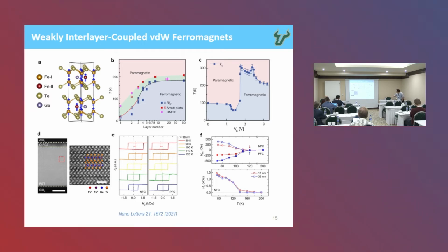So if we look at the interface between them, we see that we don't have a really flat interface between them because it becomes oxidized. So it's very likely that you may have the kind of spin disorder right here. This is more like a spin cluster, and then you have the ferromagnetic here. So it comes back to the story where you have the ferromagnetic layer and the spin cluster layer, and that coupling could possibly induce the exchange bias, right?